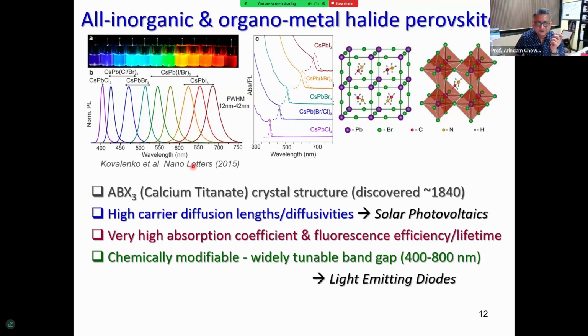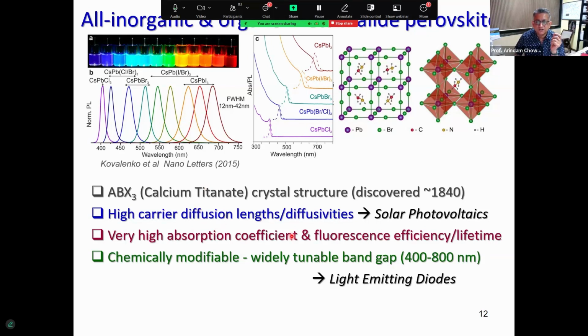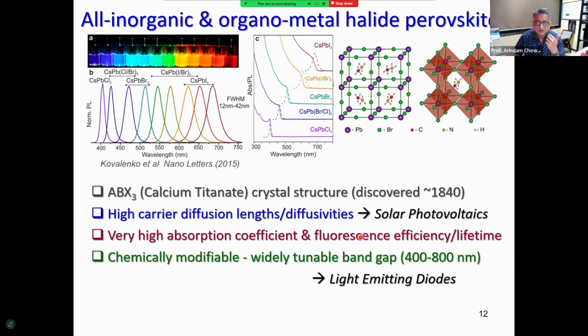Now, the great thing about these perovskites, all inorganic perovskites, is that they have very high absorption coefficient, very high fluorescence quantum efficiency and very long lifetimes. So this serves as one of the essential components that you need for solar photovoltaics. This is also related to carrier diffusion lengths or diffusivities, which people have shown are very long or very high. These diffusion coefficients are very high for the photo-generated carriers in these perovskites. That's why these perovskites are being touted for next generation solar photovoltaic materials.